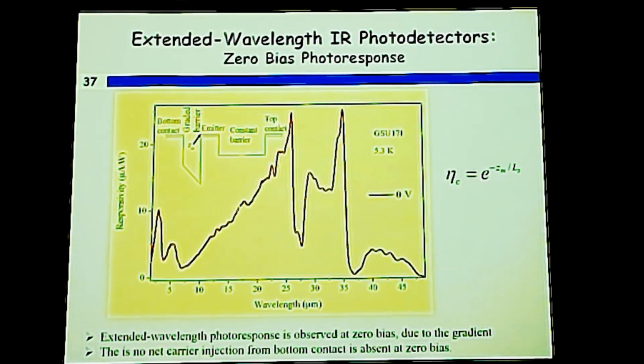So this is also more clear from this result at zero bias. At zero bias, there is net carrier flow from the emitter towards the bottom contact, because the collection efficiency for the carriers moving from emitter to the bottom contact is higher compared to that in the opposite direction. So there is no applied bias, no net carrier injection from the bottom contact, but we still see the extended mechanism. So again, the possibility is that the quasi-equilibrium Fermi level is at the same level as before, and that builds up because of the photoexcitation from the ground state to that peak split-off level.